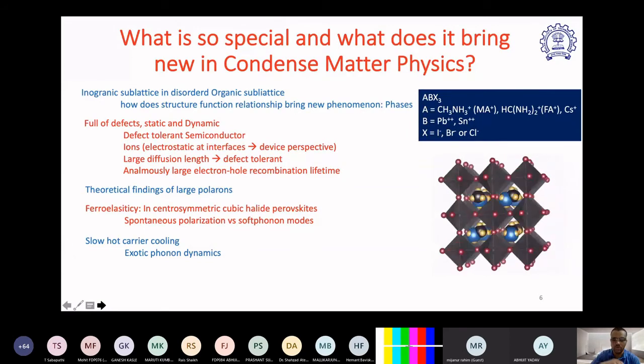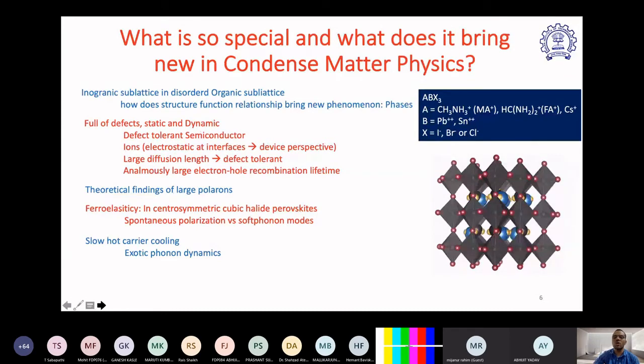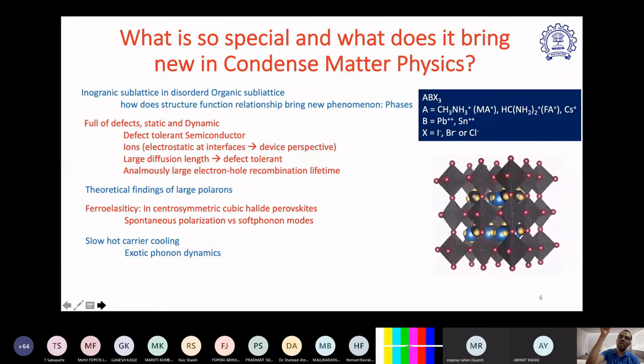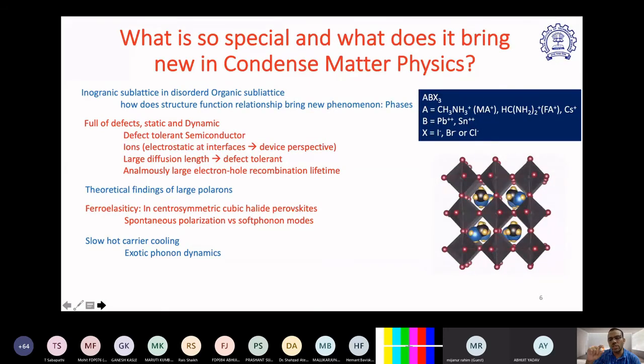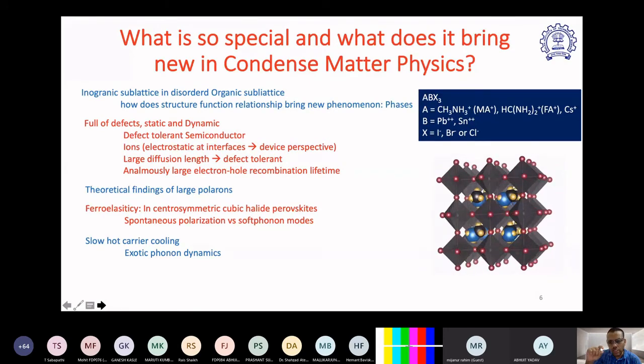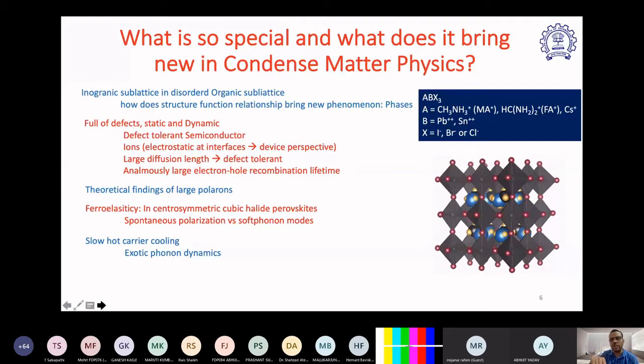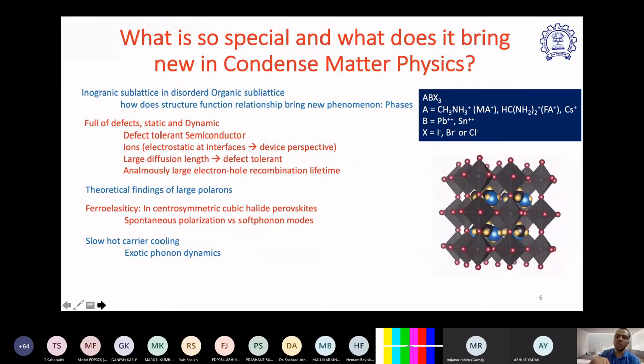In some semiconductors, this has been theoretical, and it was only recently observed experimentally. In these semiconductors, in order to relax the charge carrier within the band, intra-band relaxation requires the vibration levels to be closely spaced within the thermal energy range. Only then will it relax back. If the vibration levels are beyond the kBT range, then what happens?